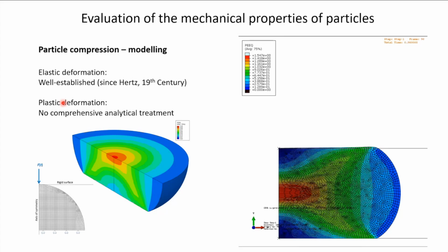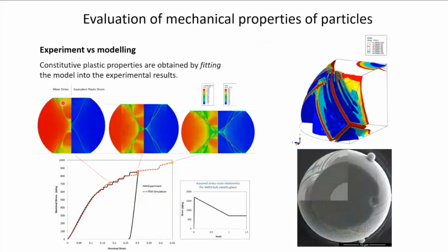So what you do then is simulate that based on different input parameters, and then you make a comparison, adjusting those parameters that you feed into your finite element analysis, against the real experimental data, and then you can work out the constitutive parameters. In this case, I think it's quite an interesting example where you use this technique in order to work out the constitutive parameters of bulk metallic glasses.